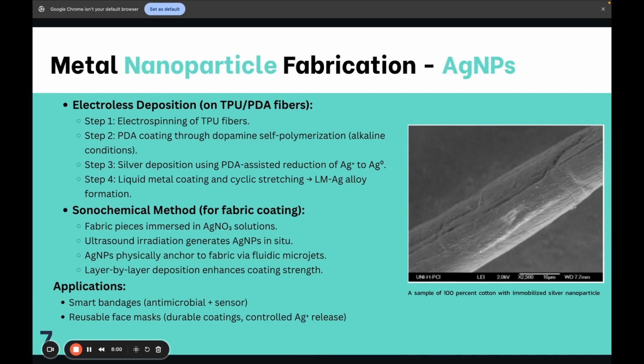TPU fibers are immersed in dopamine solution. Dopamine self-polymerizes, coating the entire fiber. Silver ions from silver nitrate are deposited onto the PDA-coated fibers. This actually self reduces silver ions to metallic silver nanoparticles. This actually helps bond liquid metal to the fiber. Liquid metal is then added to the silver nanoparticle coated fibers. Cyclic stretching is performed, which forms a stable liquid metal and silver alloy layer. The final result is a durable and stretchable membrane.